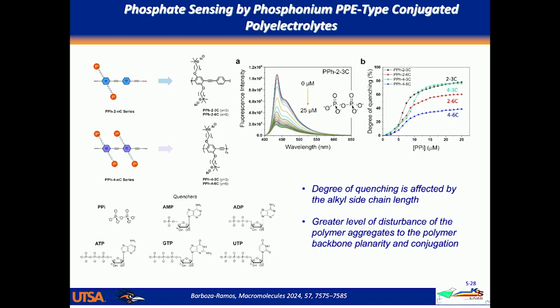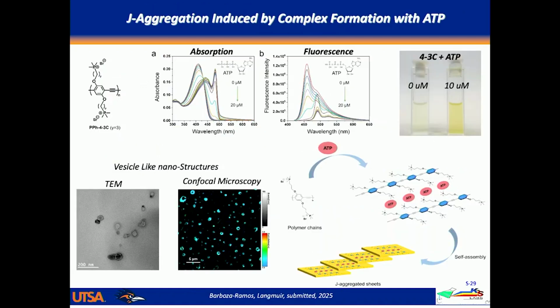But the reason I'm showing you this is that there was something that popped out of this just by accident that's kind of interesting, and we don't completely understand what's going on. But if you look at the spectra, and it's one particular member of that family, it's the structure shown here where the side chain has 3 carbons in it, and every phenylene repeating unit has positively charged groups on it. When you add ATP to that polyelectrolyte, you see some really interesting shifts in the absorption and interesting shifts in the emission. And in particular, it's this feature that we see in the absorption.